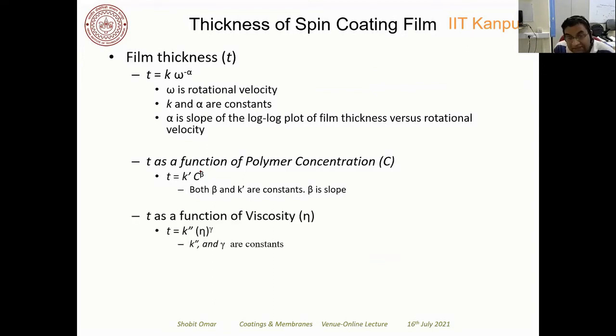Also, thickness will depend upon the viscosity, and you can see eta is the dynamic viscosity here, and there are a few constants. So if you sum these three relationships, then you will get an expression for the thickness of the coating. Like here, K, beta, gamma, and alpha are 4 constants.